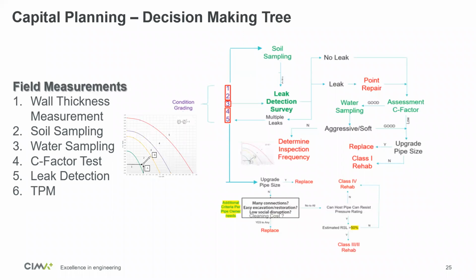So we're taking all our inspection findings using wall thickness measurement, using a correlator inspection tool based on acoustic technology, or using an EM principle, a different tool depending on the optimal tool that the pipe owner selected, doing soil analysis, water analysis, C-factor testing, and leak detection and transient pressure monitoring. This is the field measurement that we recommend. Out of these field measurements, as we saw, we can give the pipe a condition grading. And with the condition grading, we have a proposed decision-making tree and how to do it.